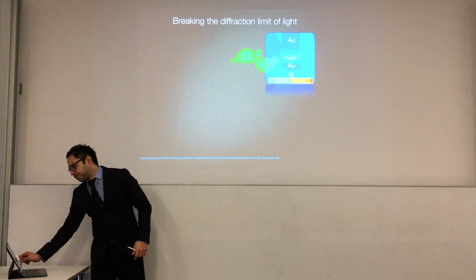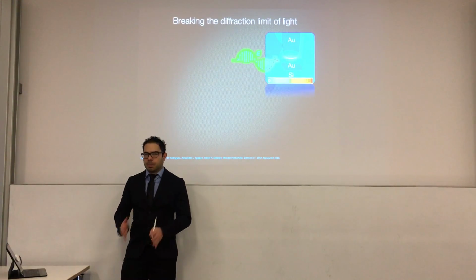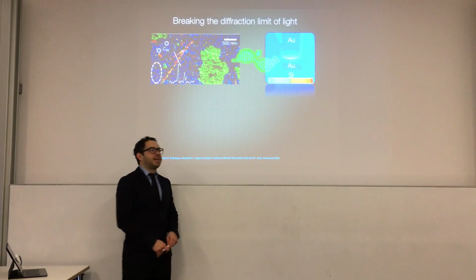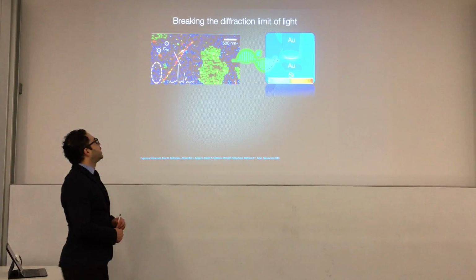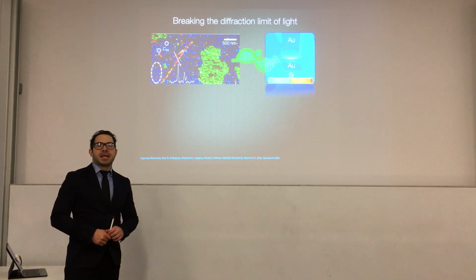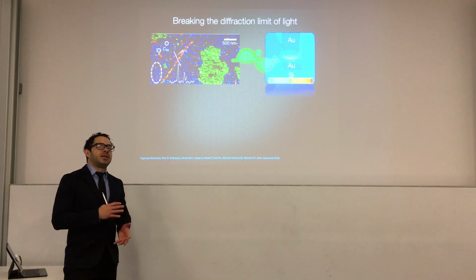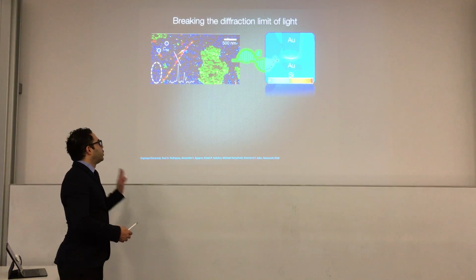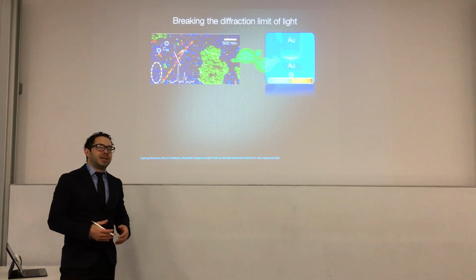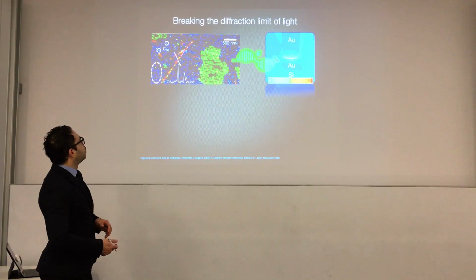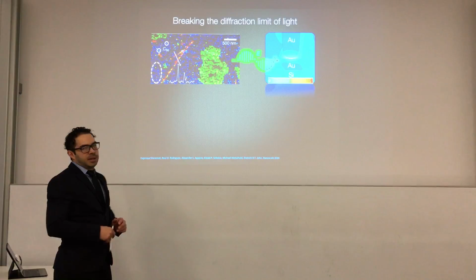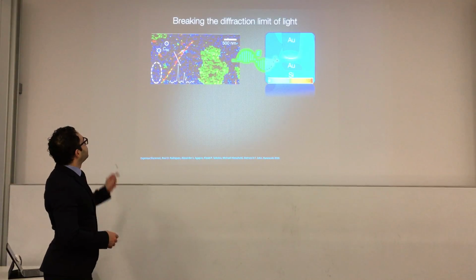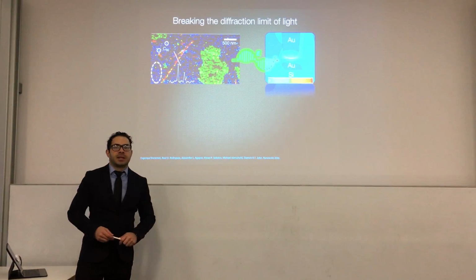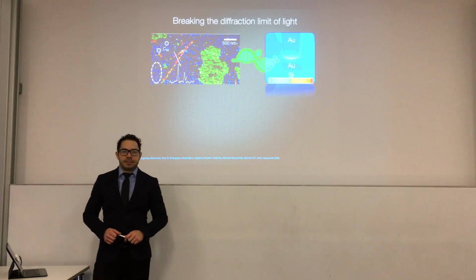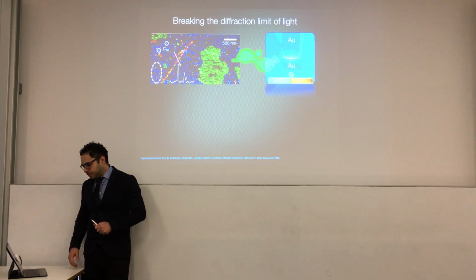So that possibility to confine light and to amplify light is the one that makes this kind of images possible. What you see here is a complicated sample because its composition is very similar. These are all carbon nanomaterials. You have graphene oxide in green color. In red, these wires that you see there are carbon nanotubes. And you have some spots around in blue color. These are fullerenes, small aggregates of fullerenes.